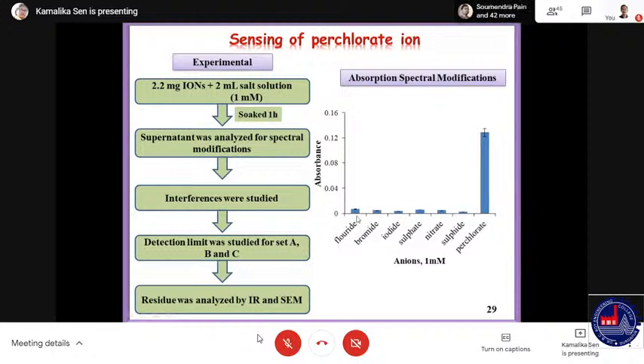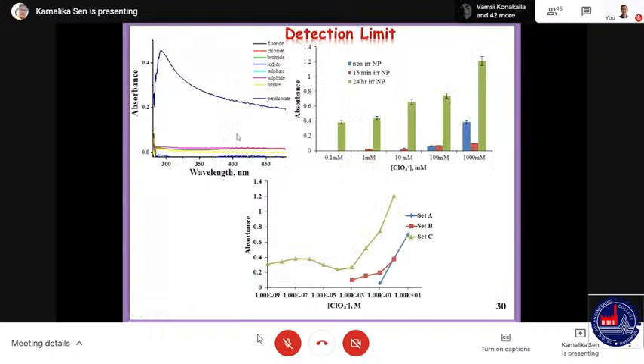So with fluoride, bromide, iodide, sulfate, nitrate, and sulfide, the absorbance was not very high. However, with perchlorate, the absorbance at around 290 or 300 nanometer increases sharply, which means that in presence of other anions, perchlorate can selectively be sensed. Near 300 nanometer, there is a high absorbance peak selectively for perchlorate, which is different from the other anions.